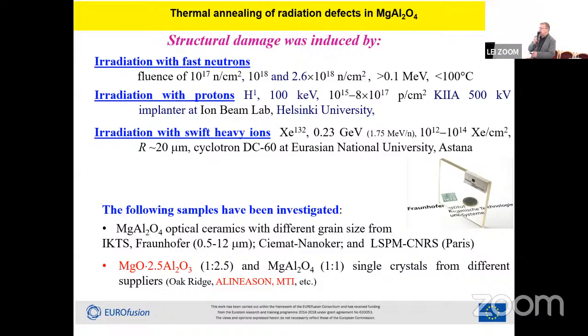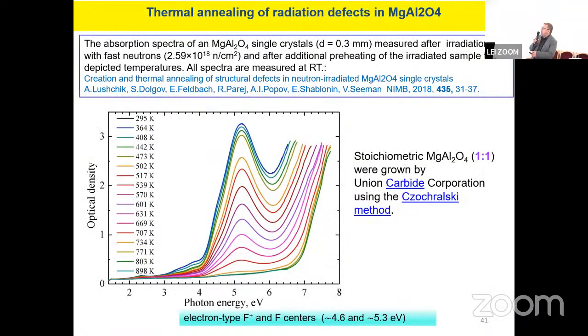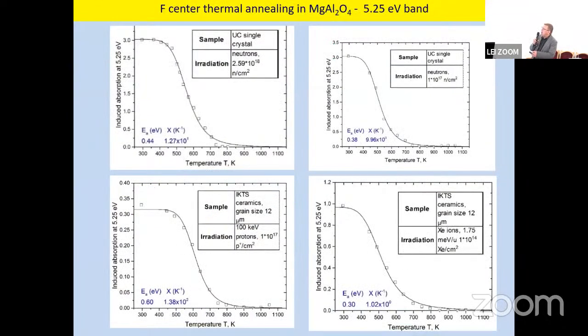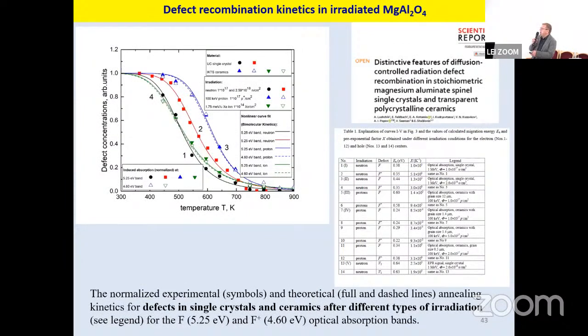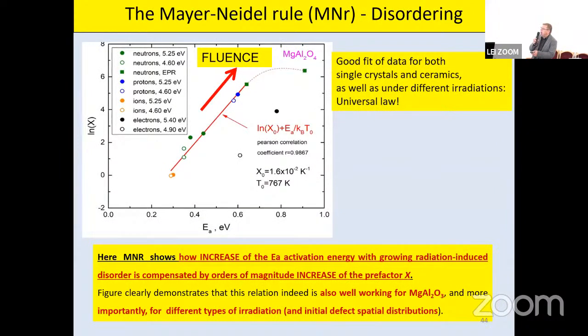So there are several companies which are using transparent ceramics with properties quite similar to the crystals, and we tested not only single crystals, but also performed similar measurements and thermal annealing for ceramics which were irradiated by ions, by protons, and neutrons. We again obtained quite similar behavior for thermal annealing. We carefully analyzed and compared all results with those available from literature, and finally we again confirm that the Meyer-Neldel rule works quite well also for such complex oxides, in both single crystalline and ceramic forms.